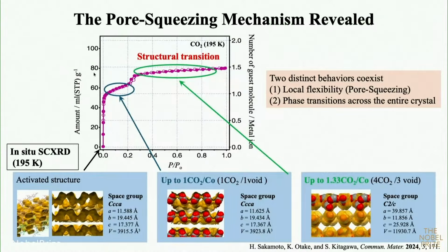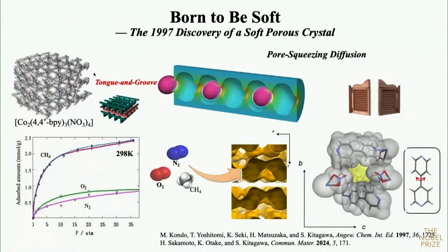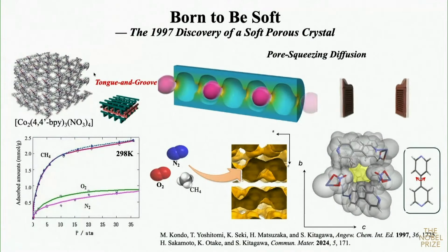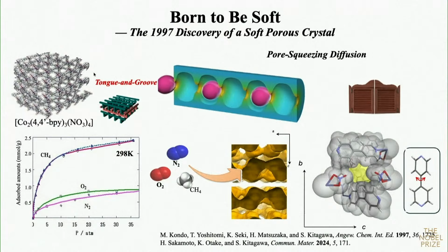So we determined the crystal structure. We can see the adsorbed CO2 molecules. Why does this happen? The result is that two distinct behaviors coexist. That is local flexibility and phase transition, global dynamics. In particular, in the local flexibility, this is the narrow channel. The narrow channel aperture is like this, constructed from bipyridine and the nitrate gate. So bipyridine rotates like this. Therefore, the gas molecule can diffuse easily. We call this pore squeezing diffusion.